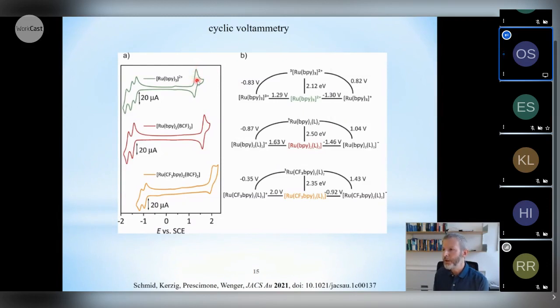And if you just focus on this metal-centered ruthenium-2, ruthenium-3 oxidation where my laser pointer is now, this is cathodically shifted by about half a volt upon cyanoborylation. That indicates you're stabilizing the metal-centered t2g-like orbitals by approximately half an electron volt. So you're opening up the HOMO-LUMO gap quite a bit, and this leads to high triplet energies. At the same time, doing chemical modifications on the bipyridine ancillary ligands, you can also achieve very high oxidation potentials for these